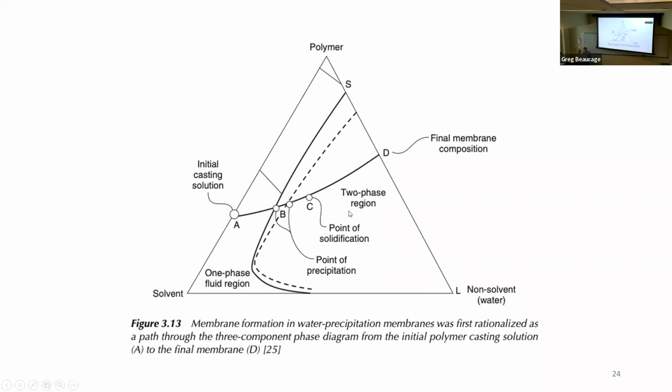So you probably want it to rapidly get to C inside the spinodal regime, which is in the middle. In the small regime that you have to pass through, you're going to get just isolated domains, which can't be leached out. So you can't really make a membrane out of that. You just have droplets. So you want the C part, the spinodal part. Somehow you have to get there fast. How fast depends on what you put in for the solvent, the temperature, and the exact details of the process. So this is kinetics. It's going to decide the structure. You have the phase diagrams laid out by thermodynamics, but the kinetics is what's deciding here.